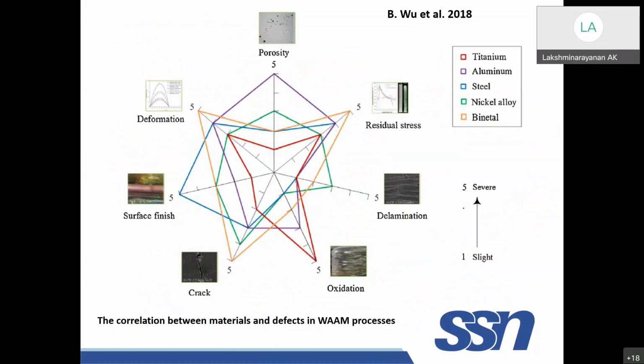We cannot generalize this. It depends on the material. That is why this graph is very important. Deformation is one of the problems, caused by the residual stress. Porosity is another problem, you can see porosity is there. Surface finish is very important, and that depends on how much deposition you are doing. You can see cracks here. Oxidation at high temperature is one problem, as some materials will go through oxidation. Delamination between layers means there will not be proper bonding.